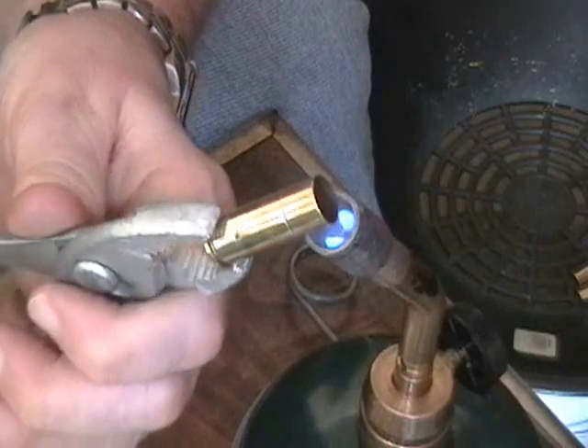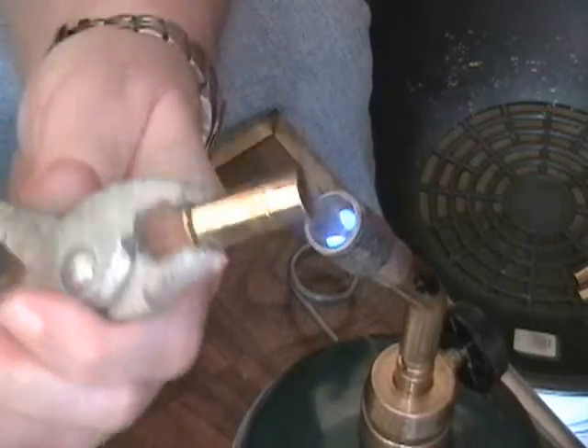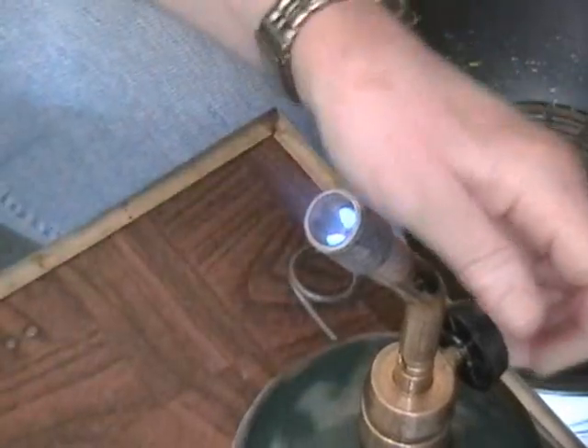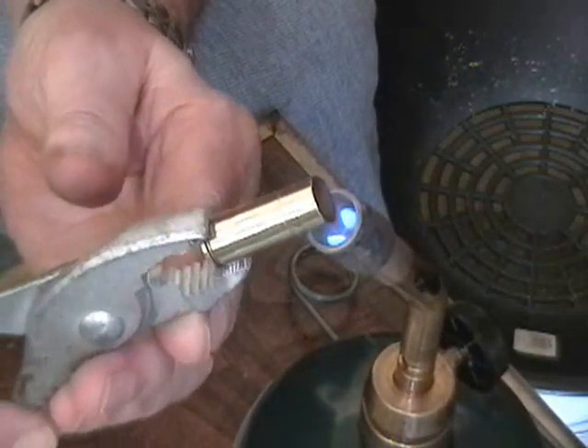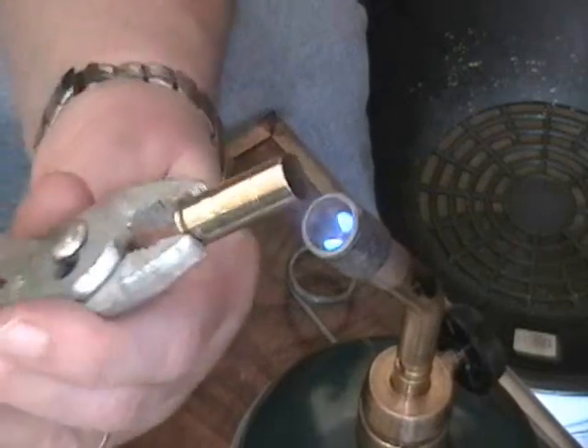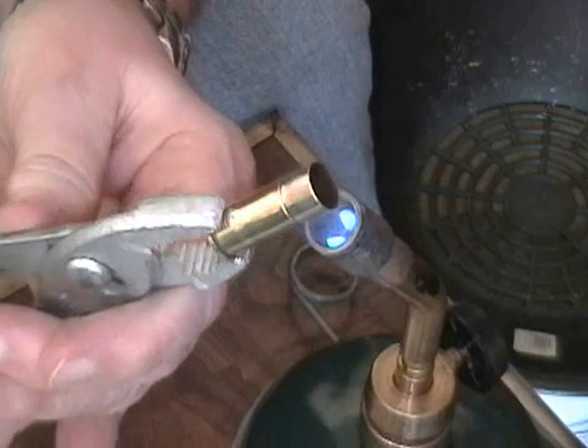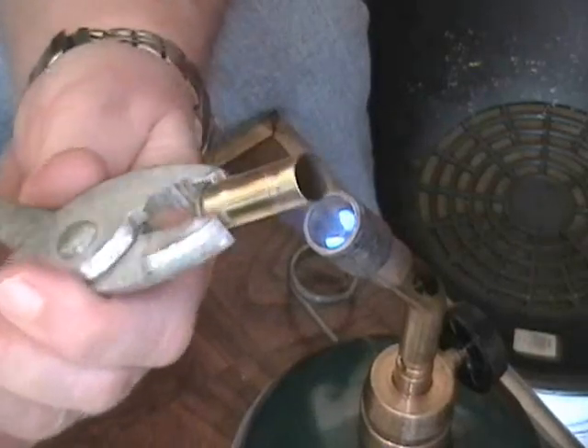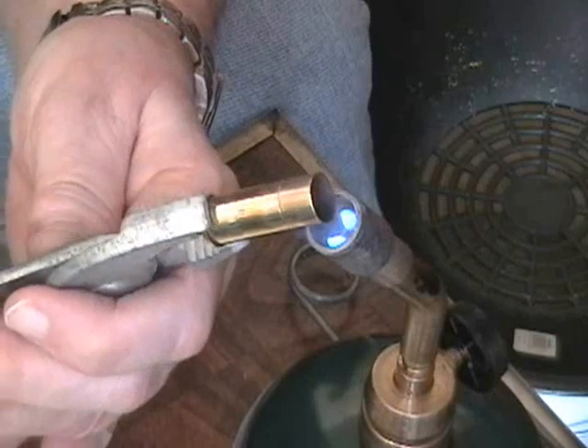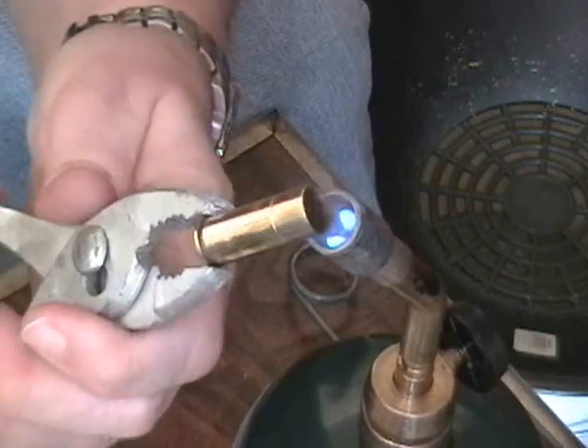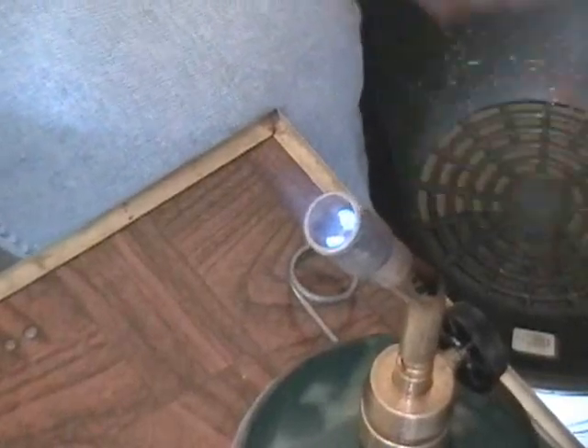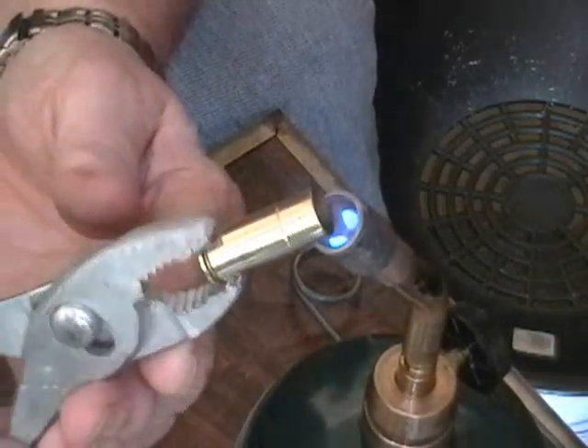I once did a trial to see how many times I could fire cases that had not been annealed versus had been annealed. Brand new cases started out, half of them after I fired them once I annealed them, and I annealed them every other time. The other half I just reloaded and shot again. Of the half that had never been annealed, I would lose anywhere from 1 to 3 cases to cracking in the case mouth every time I reloaded and fired them. So the best I got out of them was maybe 3 to 4 shots at standard loadings. The ones I annealed didn't show any signs of case cracking ever, and I still have some of them.